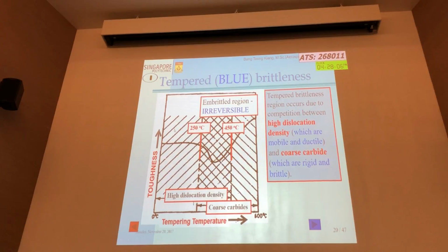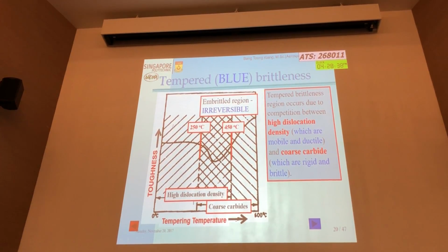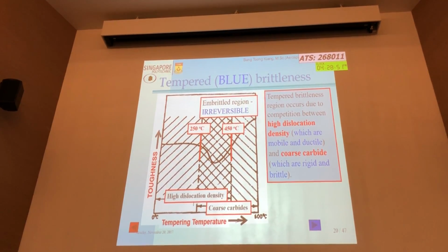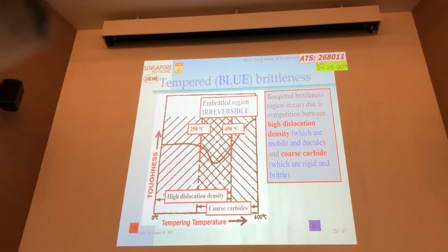So that's why you can see that if you do it at a lower temperature, there is no interaction. The carbide forms and goes to the grain boundary without interacting with the dislocation. This slash line represents dislocation. This one represents the carbide. So if you do it at this temperature, the carbide is still there, but the dislocation doesn't interact. If you do it above there, the carbide will not interact with the dislocation. It's only when you do it at this temperature that the two interact. You got me? This interaction is what gives rise to tempered brittleness, which makes the toughness reduce. So if you overcome that, the toughness will continue to increase. So that is a key thing, a key feature of tempered brittleness.